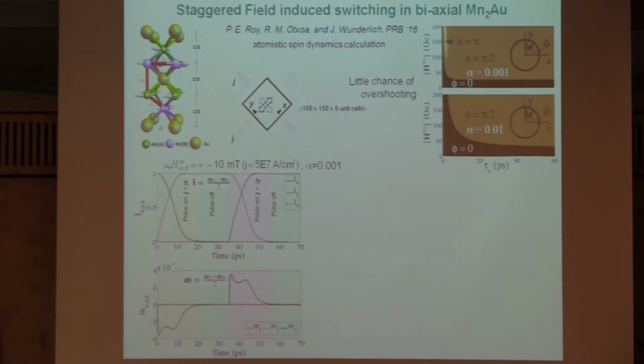As we know, in antiferromagnets, if the L vector changes, there is some inertia related to it. So if you have a very low Gilbert damping, for example, in this system, and you switch at very high spin orbit fields, there is a small chance of overshooting. But at a slightly higher Gilbert damping, the switching is very deterministic, because if it has, in principle, switched by 90 degrees, there is no torque anymore, and the system is, in principle, in its lowest energy state.